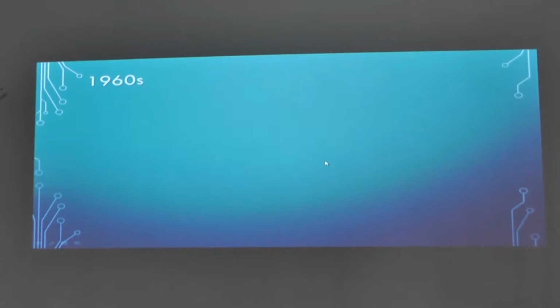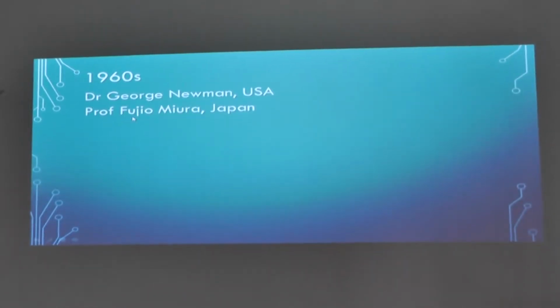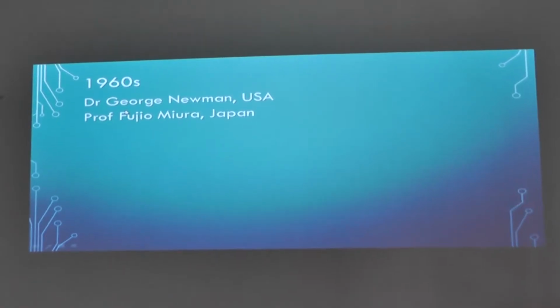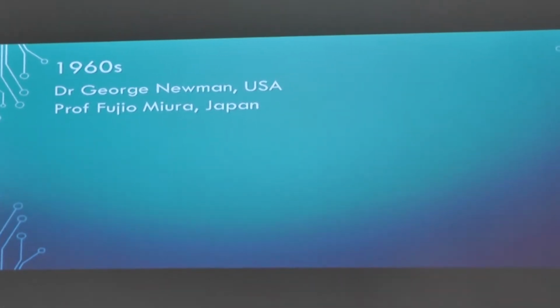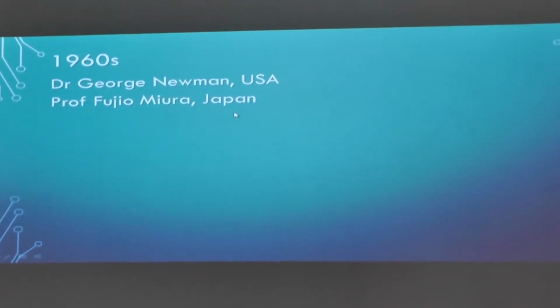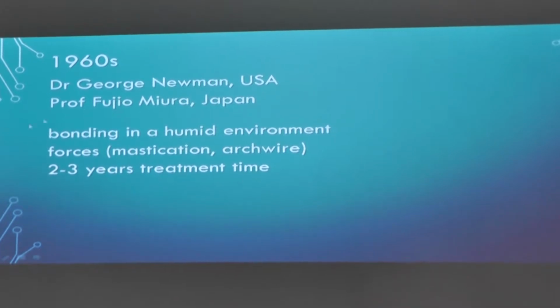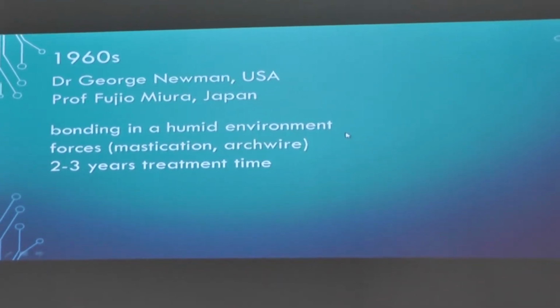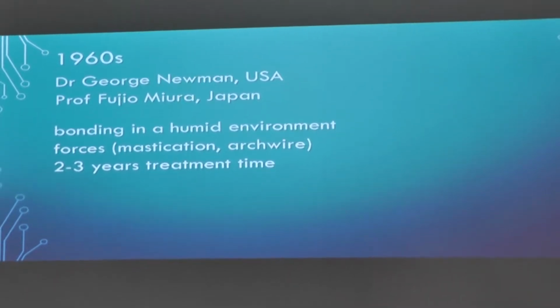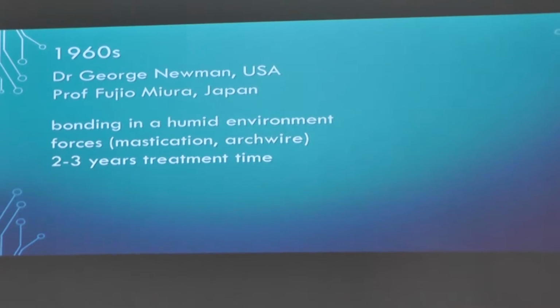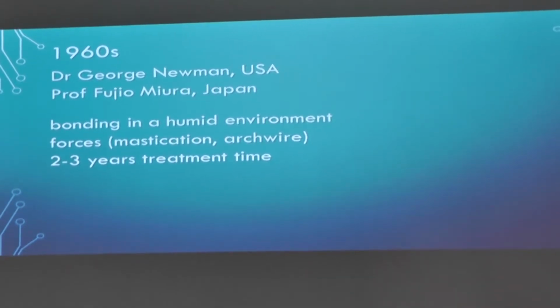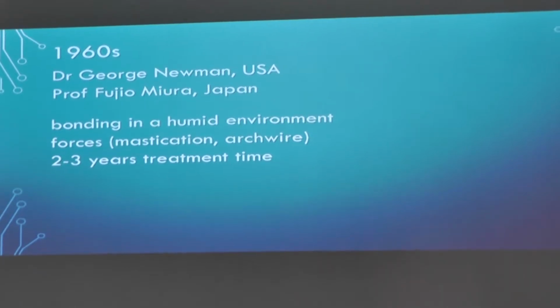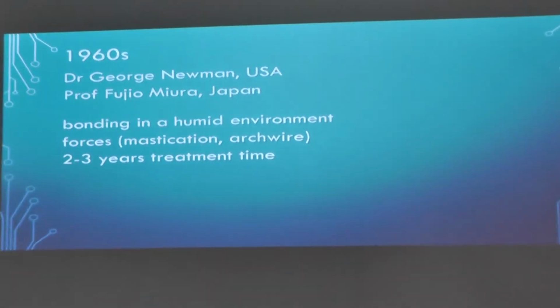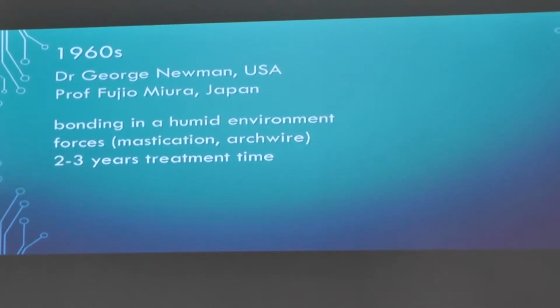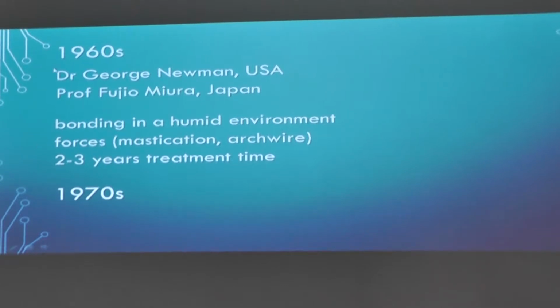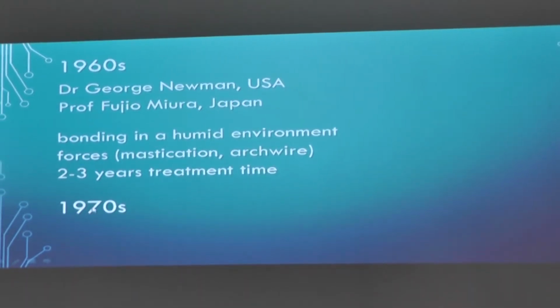And so in the 1960s, these were two orthodontists that completely separately, at the same time, started to develop orthodontic bonding systems, one from the United States and one from Japan, and they had to overcome these problems. So the bonding needed to be performed in a humid environment and had to withstand quite high forces throughout 2 or 3 years of treatment time. And one other thing, once the appliance was removed, the bonding material should also be easily removed, which is still a significant clinical problem. And so this is when the experiment started, and in the 1970s the first